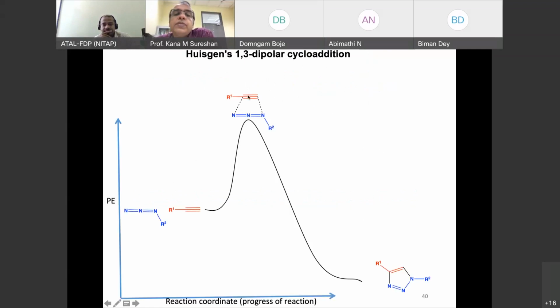Now, we can do this in a topochemical way. Why we are interested in this particular reaction is it has a high thermodynamic drive, about 65 kilocalorie per mole. It's an exothermic reaction. Nevertheless, it has an activation barrier of about 20 kilocalorie per mole. So that means just mixing azide and alkyne will not react. You need some heating. And this is possibly the transition state for this cycloaddition reaction. And if we have some scenario like this, it will automatically react without even heating much.